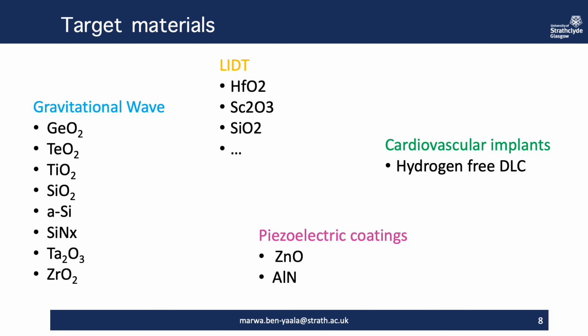So the materials we are depositing are different depending on the application. For the gravitational waves research projects, we are investigating mainly oxides along with amorphous silicon and silicon nitrides. For the laser damage, the main targets we are currently using are Hafnia, Scandia, and silica, and we are also depositing diamond-like carbons for biomedical application, and zinc oxide and aluminium nitride for piezoelectric film properties.